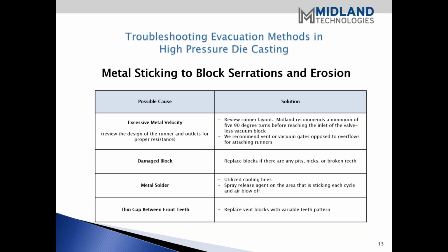So it's important to keep in mind that what you do to fix one problem can exacerbate another problem in that case. One thing, Bill, I'm going to jump back to real quick, and it was put in here intentionally, and that's the fact that trying to minimize the metal velocity can help in a lot of these cases. And one way we've discovered that helps quite a bit, die casters generally will want to add runners and create the vacuum runner system off of an overflow.